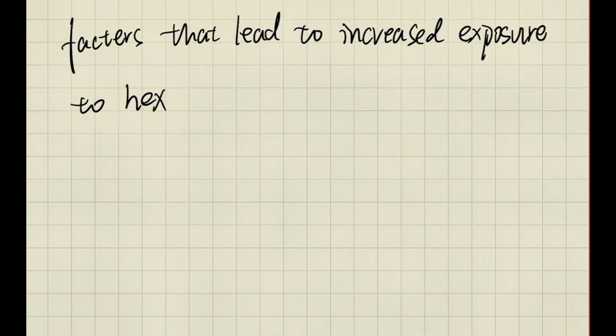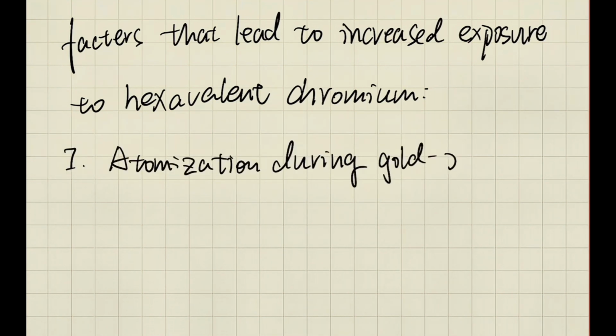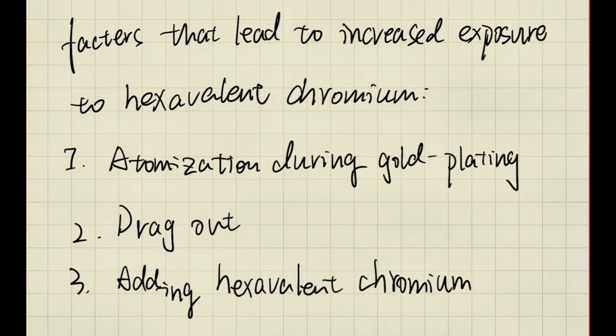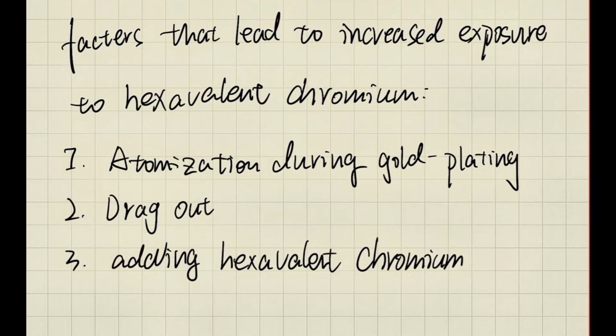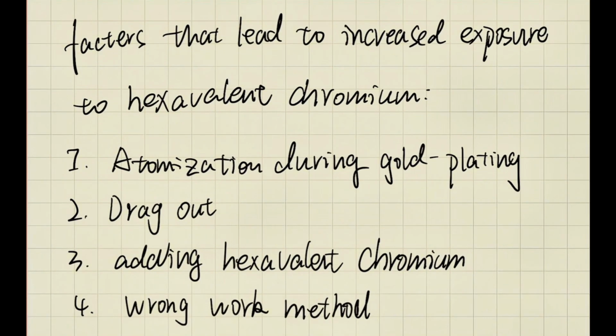In the workplace, factors that lead to increased exposure to hexavalent chromium include, first, atomization, which occurs during gold plating when hydrogen bubbles explode at the surface, causing hexavalent chromium in the electrolyte solution to form airborne water droplets. Conditions that increase atomization include higher current, longer plating time, higher bath surface tension, higher bath temperature, and increased stirring. Second, drag out. When workers insert or remove shelves or barrels from gold-plated slots, atomization and overflow may occur. Third, adding hexavalent chromium. Adding chromic acid and chromium powder solution to the gold plating tank may cause overflow or produce dust or atomization. Fourth, work method.